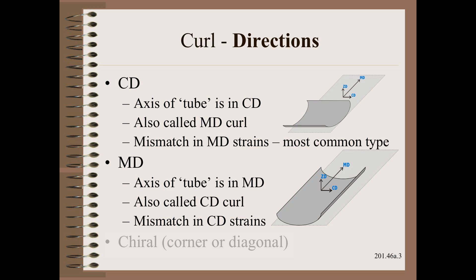Whenever you have the first curl direction, you also tend to have curl in the other direction to a smaller degree. Finally, there is chiral curl. This is a curvature on the diagonal, or angle, sometimes called corner curl. It is most common with anisotropic materials where the principal axis of the top and bottom are not aligned.